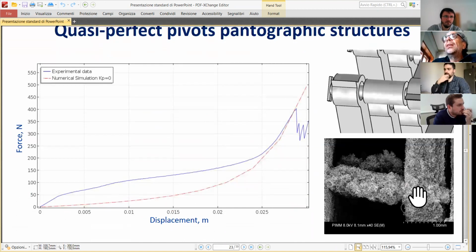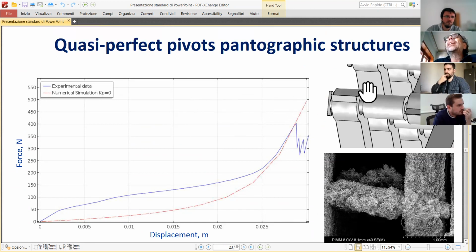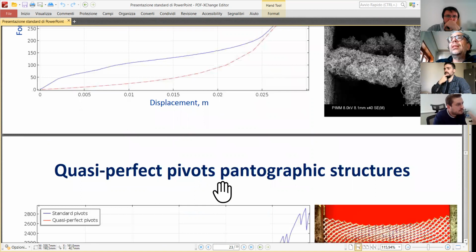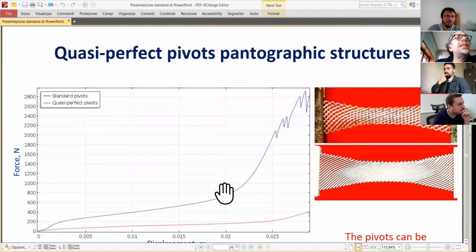Okay, then we made experiments with so-called quasi-perfect pivots, which are pivots that are nearly perfect, but not printed as they should be. In red, you see the plot of the numerical simulations forecasting the behavior of a perfect pantographic sheet, and in blue, you find the experiment. So you see that more or less, we are going towards the desired behavior in our experiment. And this is the experimental plot also after rupture, when you have the famous phase transition I was talking about.